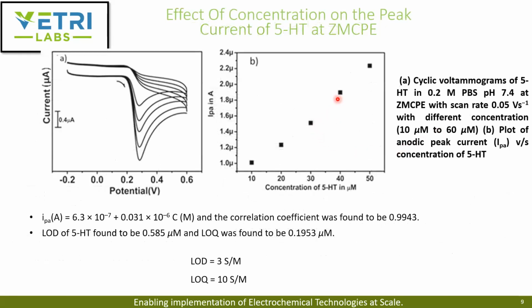Then they looked at the effect of concentration on the peak current of 5HT at the zirconia modified carbon paste electrode. They used a linear concentration range from 10 micromolar to 50 micromolar. As they increased the concentration, there was an increase in the current, but with a slight shift in the potential towards the positive side. They extracted the peak current IPA and plotted it versus the concentration, and formed a linear regression equation with a correlation coefficient of 0.9943.